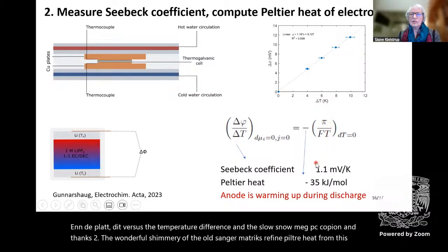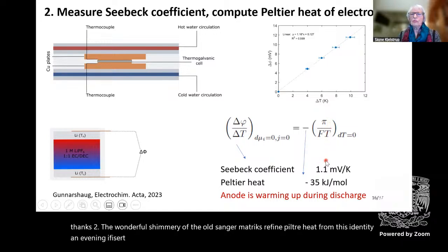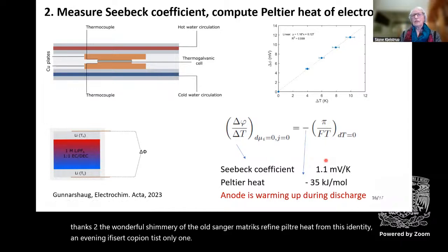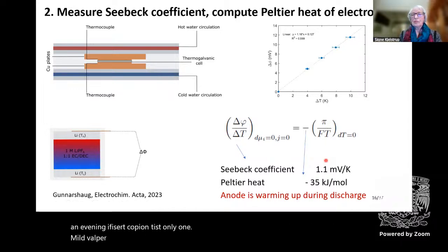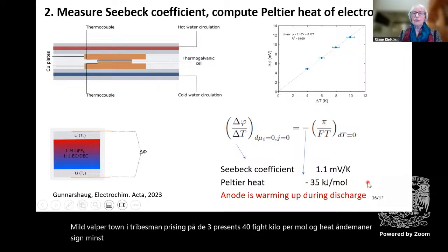And even if the Seebeck coefficient is only 1 millivolt per Kelvin, it's surprising, but it represents 35 kilojoule per mole of heat. And the minus sign means that the anode is warming up when you discharge the battery.